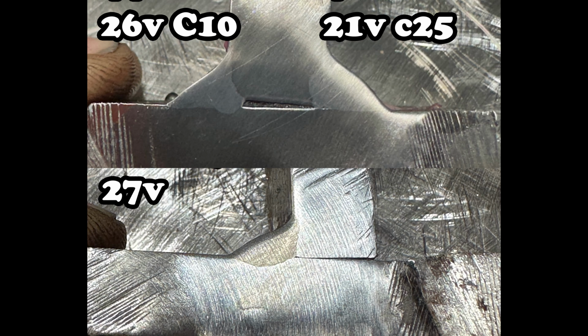And you look at that dual shield on the bottom, and it is definitely better than C25 with short circuit, but it's not honestly as good as spray in my opinion. And keep in mind that both spray and dual shield require super high 26, 27 volts, a lot of wire feed, and a lot of amperage. The spray honestly was probably running a bit more amperage, but which one would you rather have?